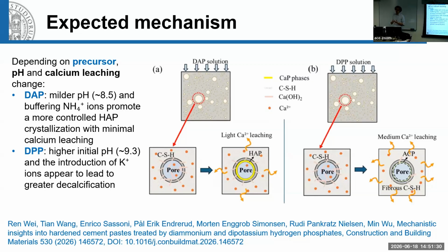So it's true that we want to form a calcium phosphate for the reasons that I explained, but when this calcium comes from the CSH especially, and calcium hydroxide or calcium carbonate, then it might become problematic, okay? You don't want to consume your CSH to form the calcium phosphate, because otherwise you strengthen your material, but you take out strands from the material itself. So it becomes counterproductive.